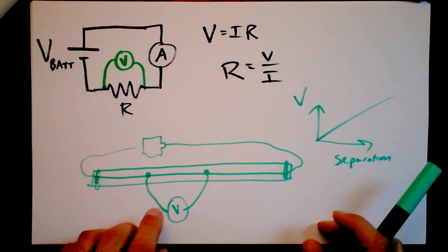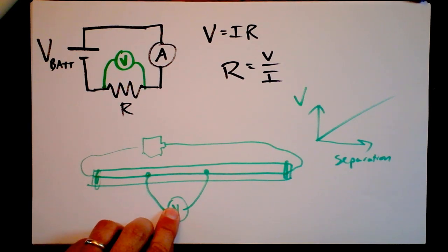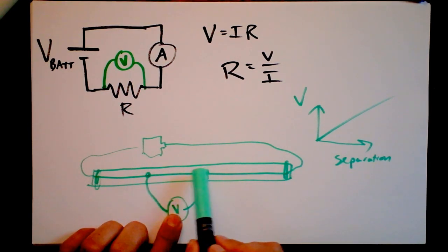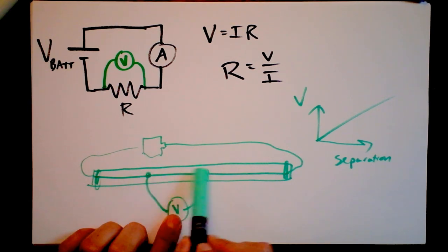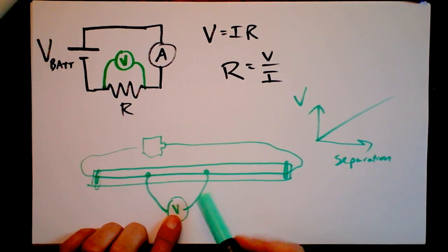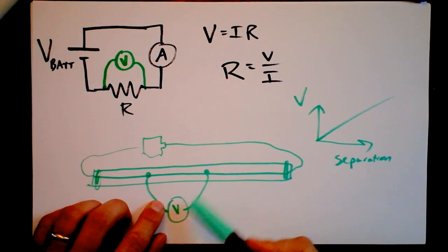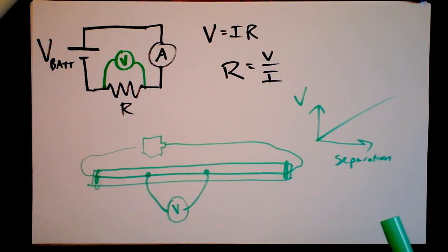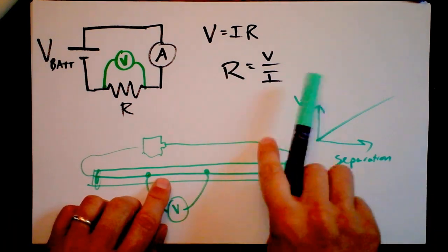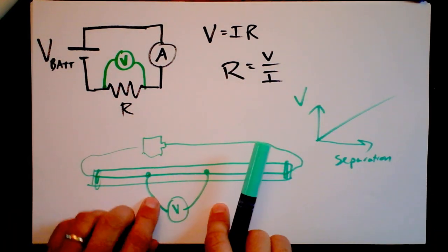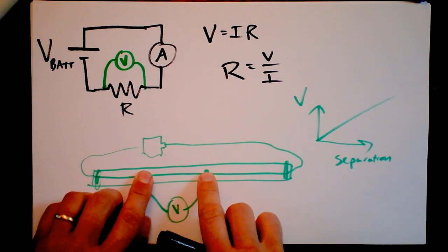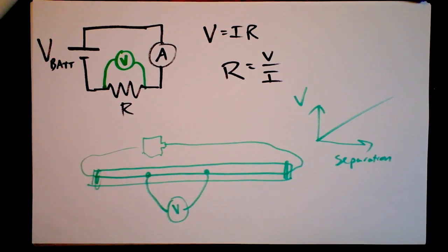Assuming you've got a good voltmeter, right? You've only got one path for the current to flow. So the current could be measured anywhere and you need to get as close as possible to the sample with your voltmeter. Now, the nice thing is you're not going to have a big current through your voltmeter because this is really useful for a very, very conductive thing. So your voltmeter is very, very high impedance. It's got a lot of resistance built into it. So your voltmeter is not going to impact your measurement very much. It's not going to increase the current that would be coming through here, which if it were a low resistance voltmeter connecting it in parallel with a bit of your testing material, it would impact.